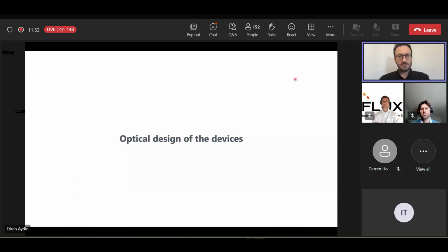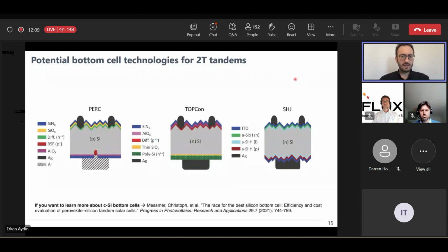All right. Well, I'll talk a little bit about what kind of progress we have made so far on the optical design of these devices, because the light coupling is quite important to make efficient tandem cells. And for sure, the light coupling is highly dictated also by the bottom cell choice, and there are three mainstream crystalline silicon technologies at the moment in the market, and the most dominant one is the PERC. The typical PERC process involves a textured front contact, a planar rear side, usually a nitride insulating layer, and silver contacts diffused through local openings, and they also diffuse through the front contacts.